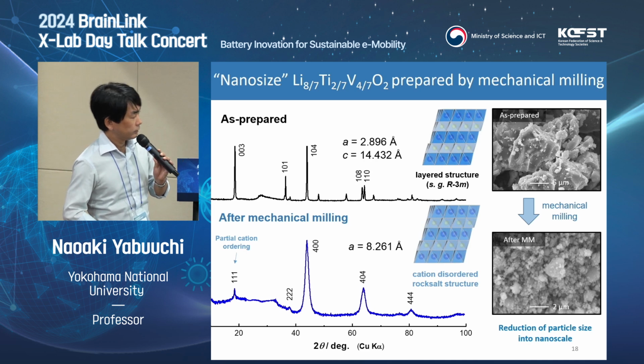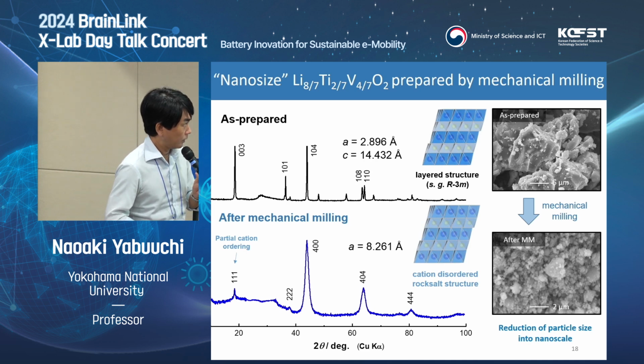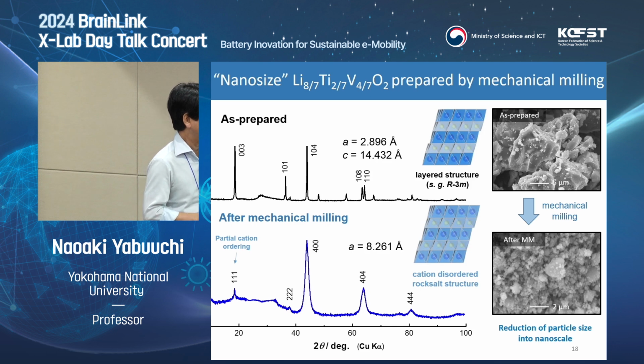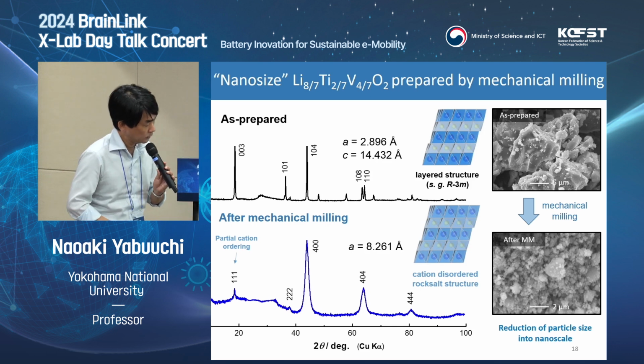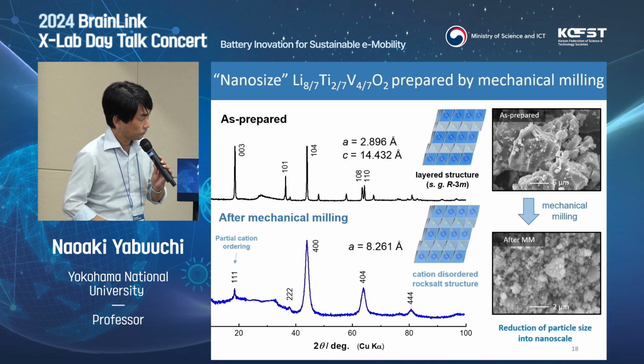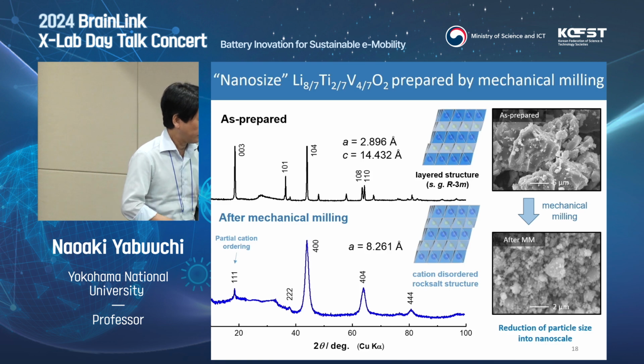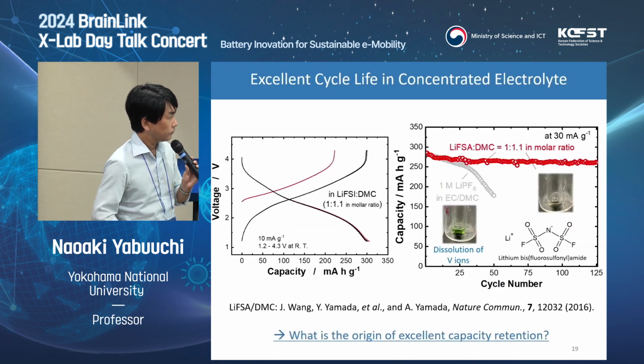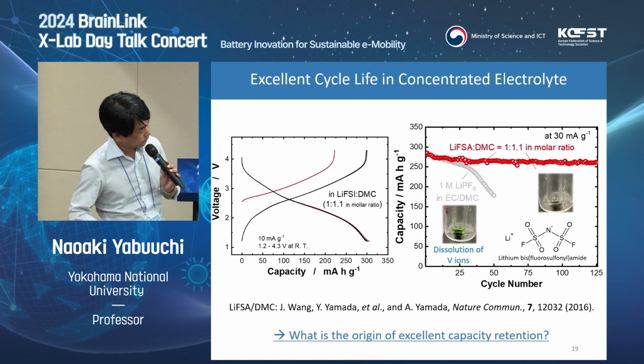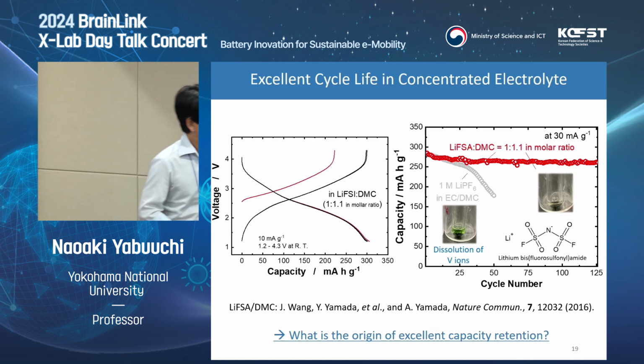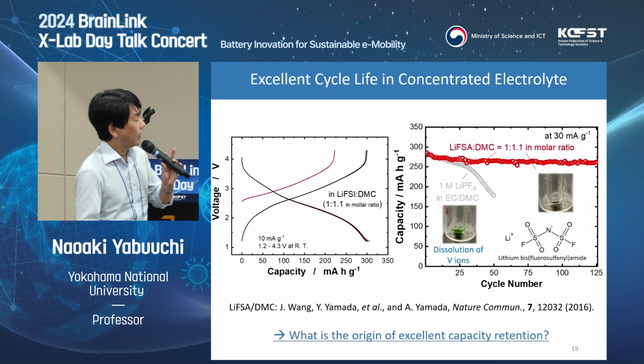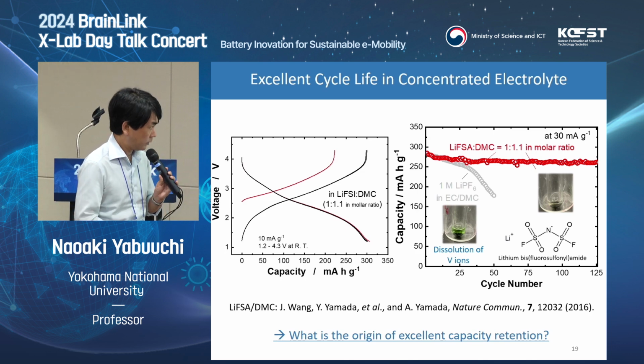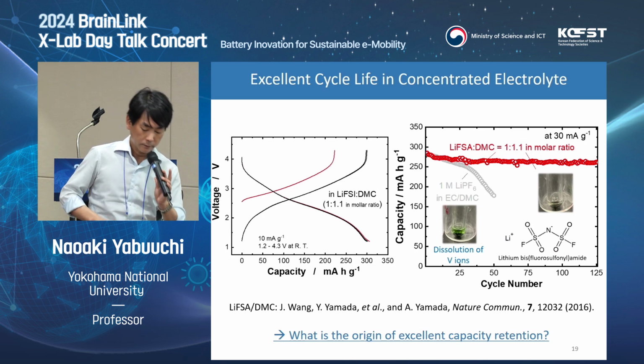So now we synthesize rock salt electrode materials. The chemistry is vanadium ions, lithium-rich vanadium chemistry. This sample shows very large reversible capacity, and also this sample is actually a low crystallinity rock salt type material synthesized by high energy mechanical milling. So this sample shows very high reversible capacity and also very good capacity retention. Again, similar to manganese ions, pentavalent vanadium ion is a highly soluble chemical in electrolyte solution. Therefore, highly concentrated electrolyte solution effectively suppresses dissolution.